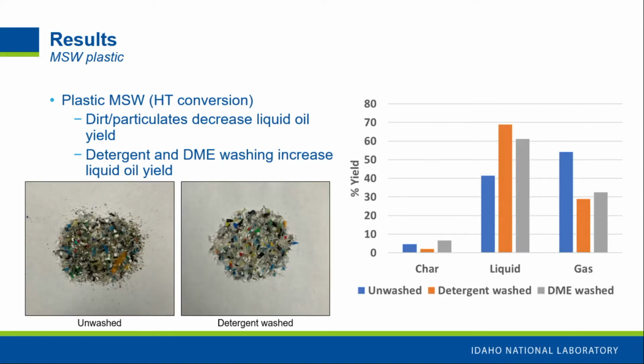So for our MSW plastic, kind of switching gears, this was for our microwave-assisted pyrolysis experiments. Like I said earlier, our most common contaminant was this dirt and particulate that's present in the plastic. And so we took two different approaches. The first one was just a really simple detergent and water, like dish soap basically, just washing away all of that dirt and particulate. And the other is using a solvent, dimethyl ether, and someone talked about that earlier in some of these sessions. Thank you. We used DME to basically wash this, and the nice thing about this DME process is that you get a dry plastic afterwards, and you can recycle it. Like 98% of the DME can be recycled, so that's really interesting to us.